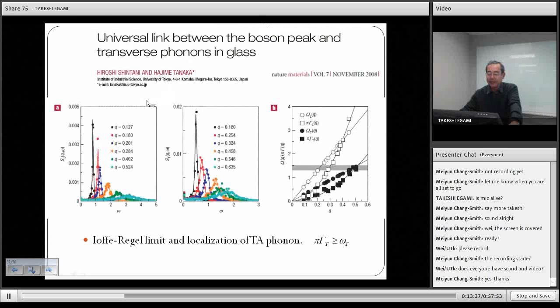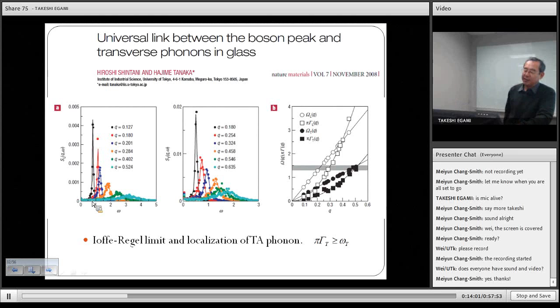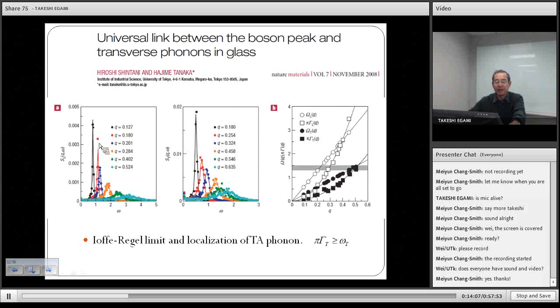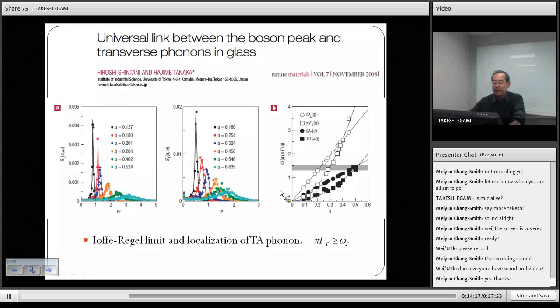This is another example in glass. As you can see, at low frequency, phonons are pretty sharp because low frequency phonons are long wavelength phonons. So if the wavelength is long enough, then the atomic structure doesn't matter. The whole thing behaves like a solid. So detailed atomic structures are not that important. So the phonons are more damped than in crystals, but still well defined. But if you go to high frequency, they become very, very broad, like that, right? So low frequency phonons are propagating, but high frequency phonons are localized.